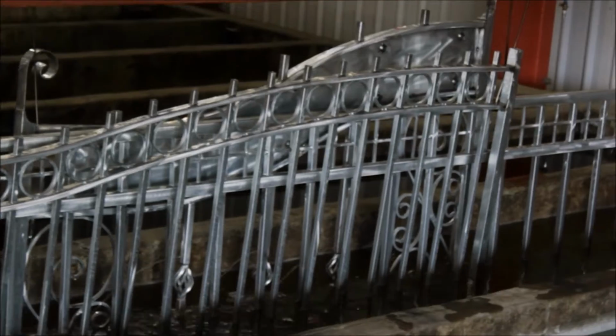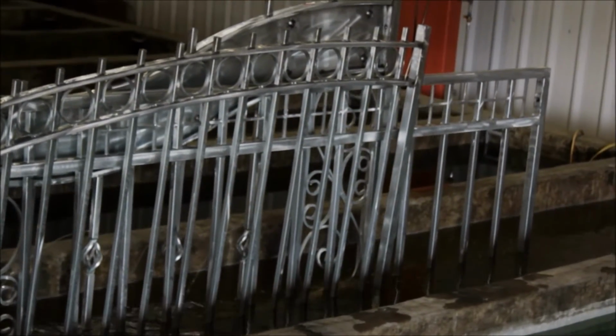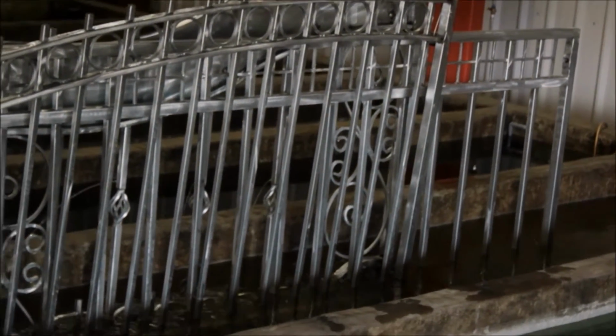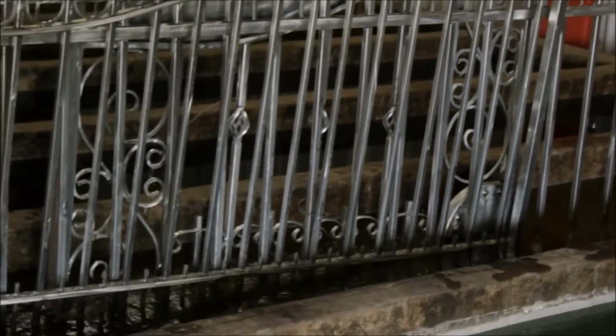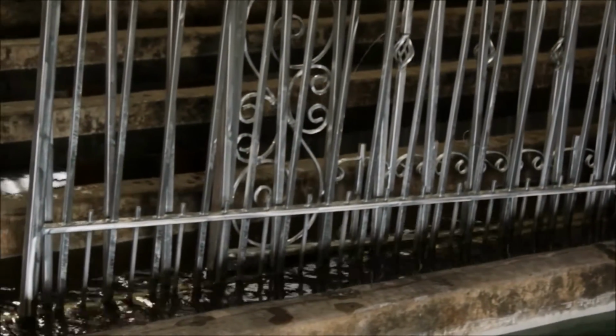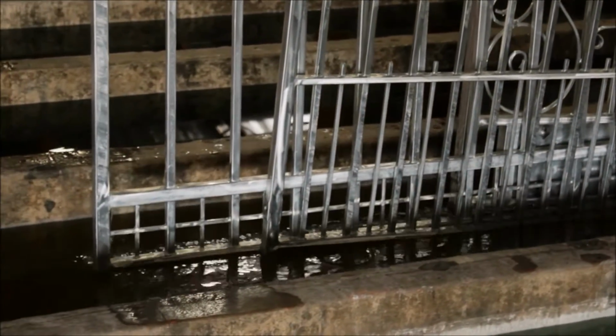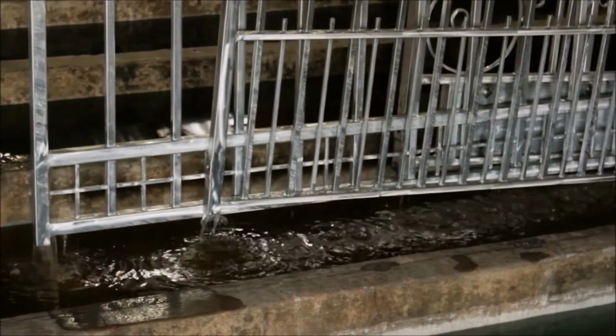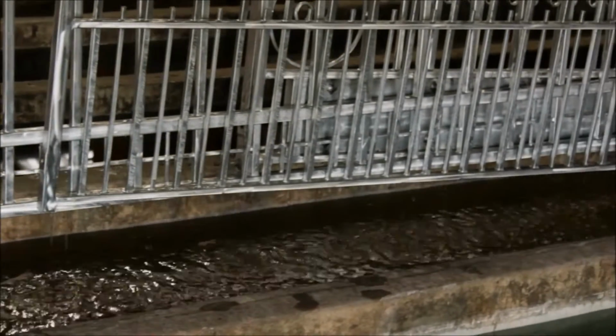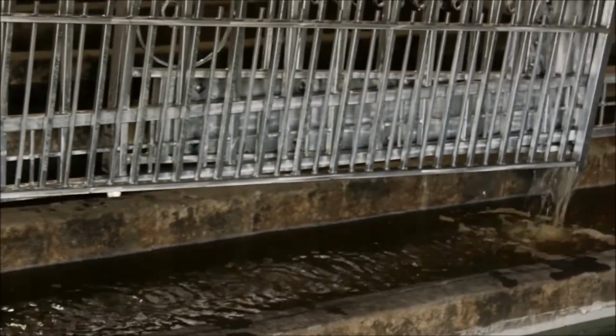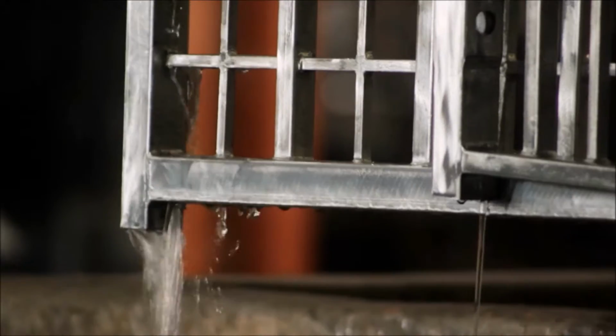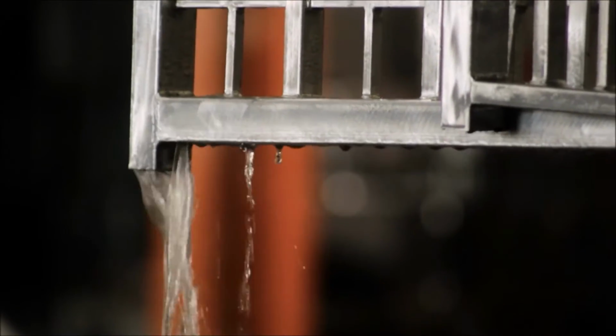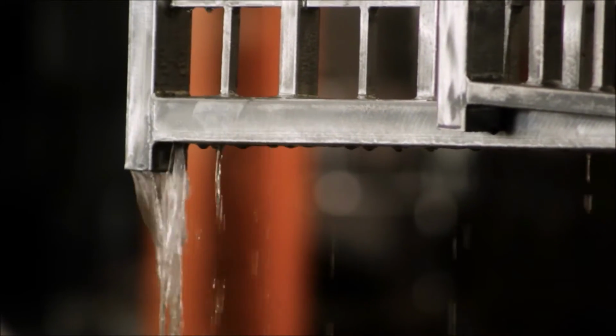There's lots of gate fences that I've experienced in America and Australia that don't go through this process, and after a while the paint just chips off very easily. Powder coating comes right off, because there's no bonding at all. So as you can see now, they're taking it out of the activate bath, and it will go now into the phosphate. The zinc phosphate gives it that surface that the powder coat can bond to. Basically cleaning, prepping and treating the surface of the zinc for powder coat.